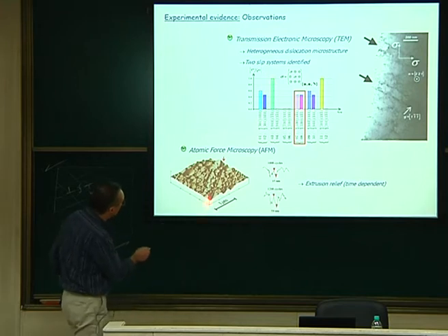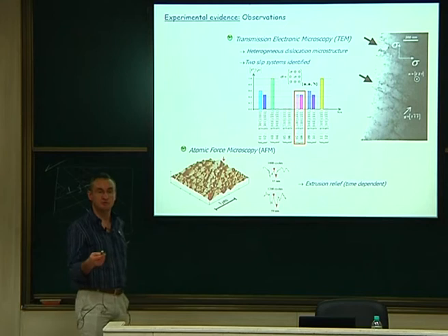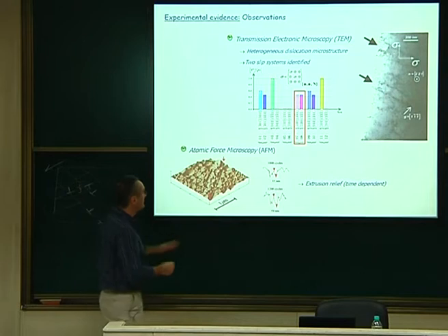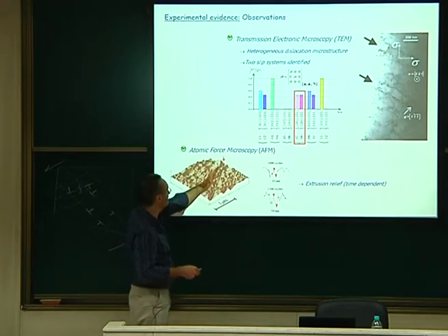But although that, you can see the profile here, which is typical of a band, similar to what we saw this morning with the channeling in irradiated materials. But here, this is not channeling. This is because of a persistent slip band, because of this guy here. There is some extrusion or intrusion which is formed at the surface.